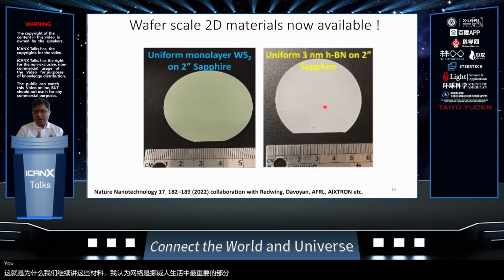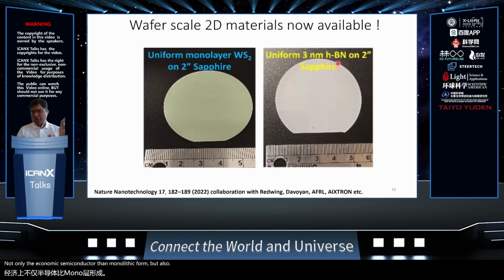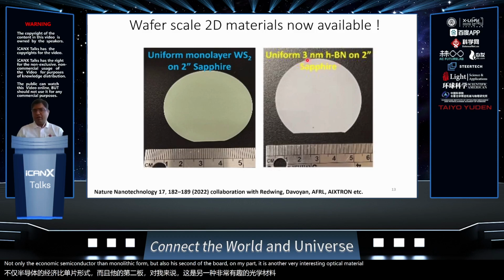You can actually grow these materials over large areas, over wafer scales, not only the excitonic semiconductors in monolayer form, but also hexagonal boron nitride, which is another very interesting optical material, with controlled thicknesses of about 3 nanometers and even below.